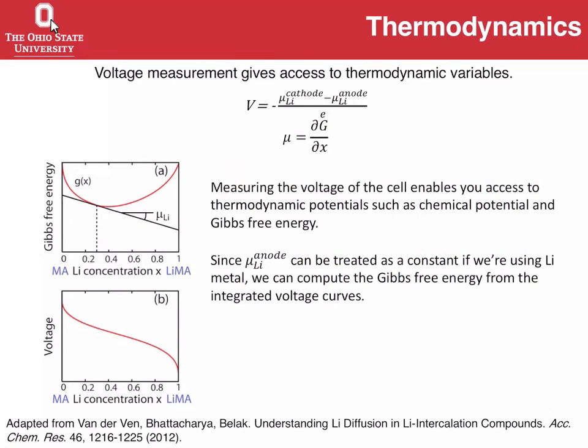If you have this sort of profile, once you cycle your battery and you're lithiating or changing the concentration of your lithium and you read your voltage curve like this, what it's telling you is exactly the slope of your Gibbs free energy plot as a function of lithium concentration. It's just the slope of that curve. So it's just delta G divided by delta X. So that gives you your chemical potential, and you can relate chemical potential to the voltage, right? The voltage is your measurement.